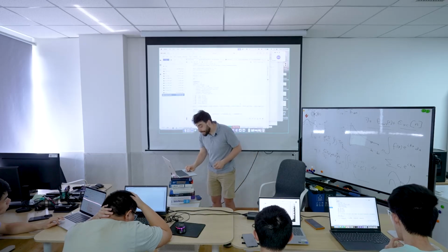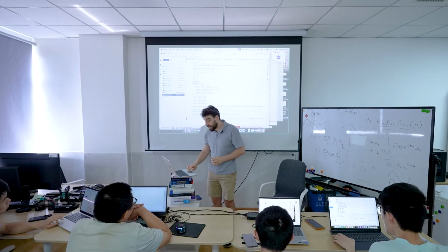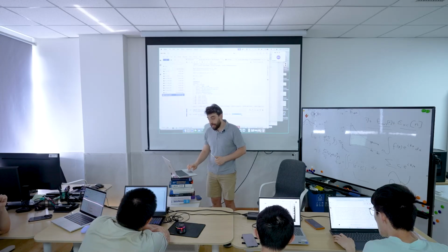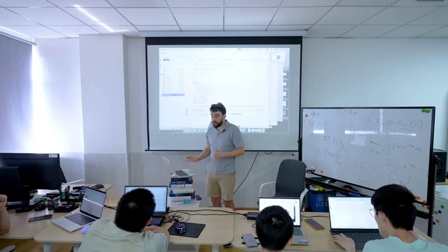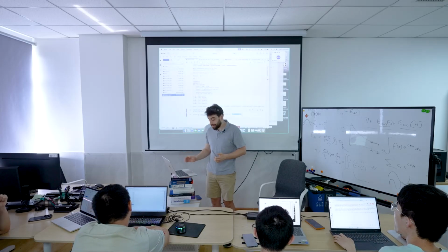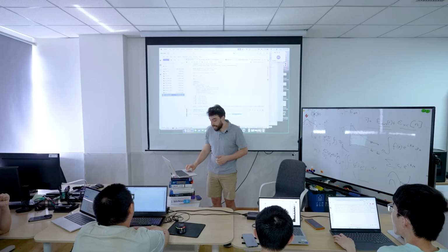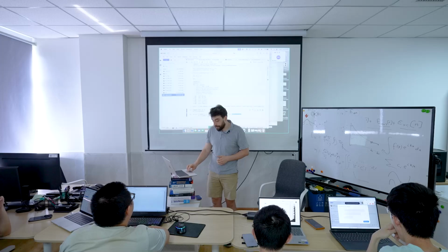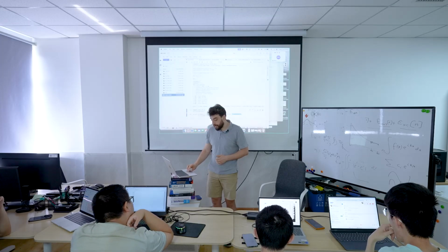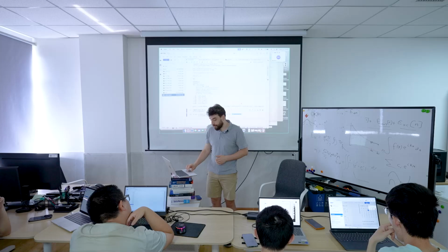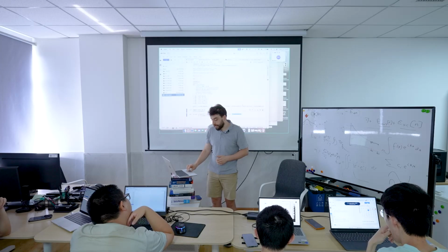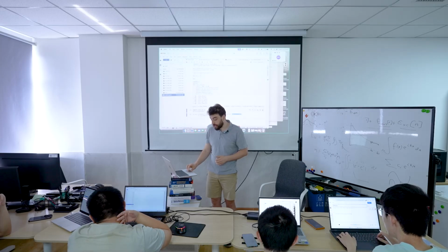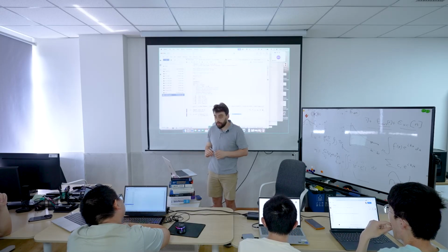So in this case, what do I think is accurate enough? I think that this one is accurate enough, 7 times 10 to the minus 2. It's probably good enough. It's not perfect, but it's good enough. So what does that correspond to? Well, this first number is the difference between this one and this one. This is the difference between this one and this one. This is the difference between this one and this one. This is the difference between this one and this one, right? So basically by the time we get to this, which is 300, 400, 500, 600 eV, we're converged.